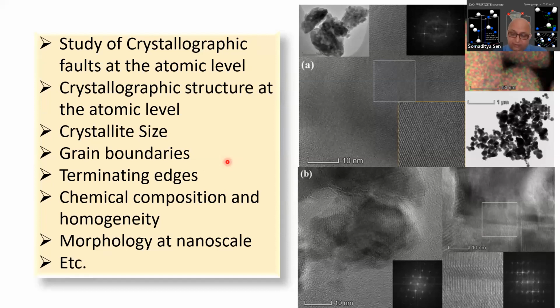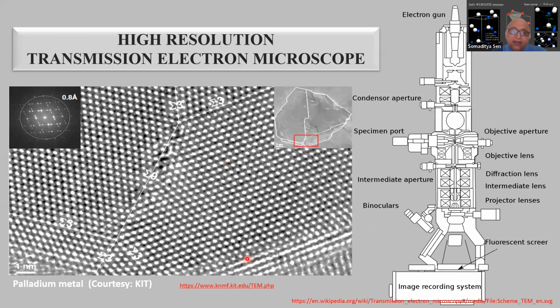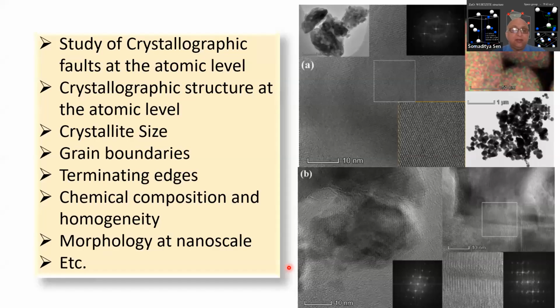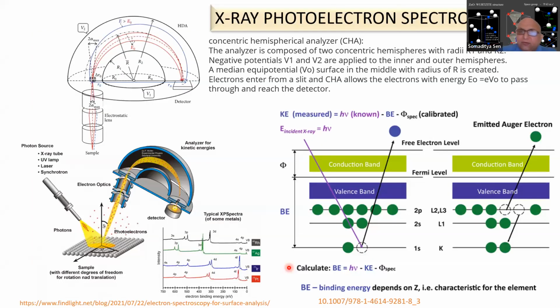What are the terminating edges? Suppose this one, what is the edge? By calculating this d-spacing, we can find out which plane it corresponds to. So then we can find out which is the terminating edge of these nanoparticles. And then the chemical composition, homogeneity and the morphology at the nanoscale can be found out. Now we come to another very important aspect, to understand the charge state.